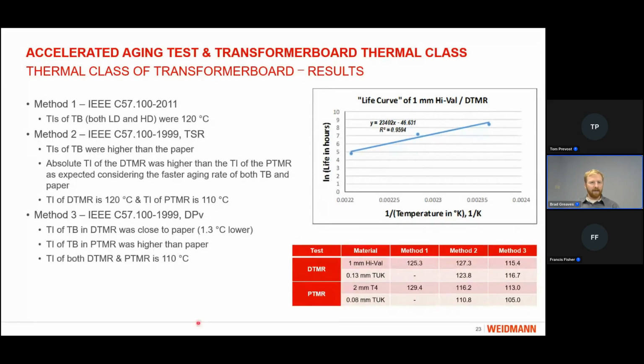Looking further onto method 3, this is using degree of polymerization with a DP of 200 as your end-of-life criteria. We see with the distribution ratio, they're close. However, the board, high val, is slightly lower than the thermally upgraded paper in this case. In the power ratio, we do again see the board, the 2mm T4, having a slightly higher thermal index than the paper. And for all of these, we see a thermal index of 110 degrees C, rounding down, with the exception of the paper in the power materials ratio.